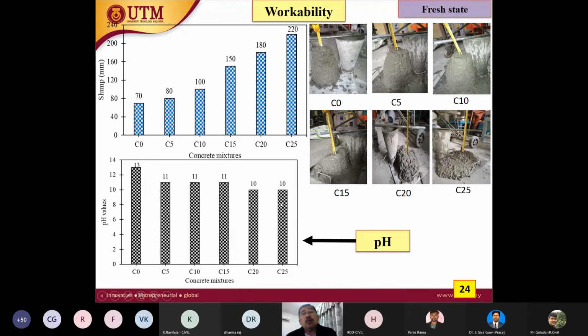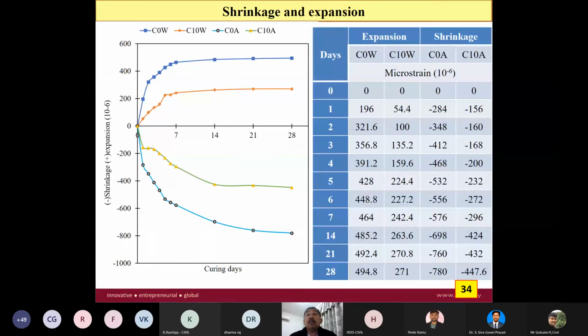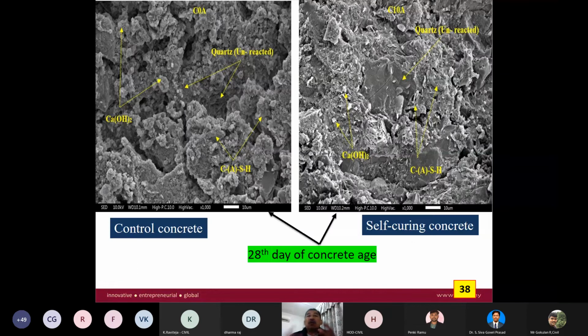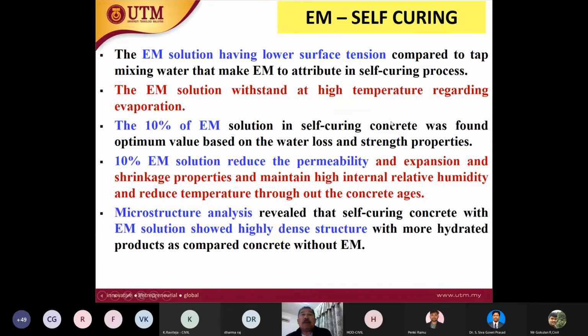So this is probably good for bio concrete, bacteria concrete, because if the alkaline environment is very high, it may not work well for the bacteria. And it also reduces the shrinkage and expansion. Why? Because the microstructure of the concrete becomes different by using EM. So we can see that this is control concrete without effective microorganism. The right one is with EM. So these are our findings, which means that EM reduces the permeability. Once it reduces the permeability, it can increase the durability aspect. So this is what we found.